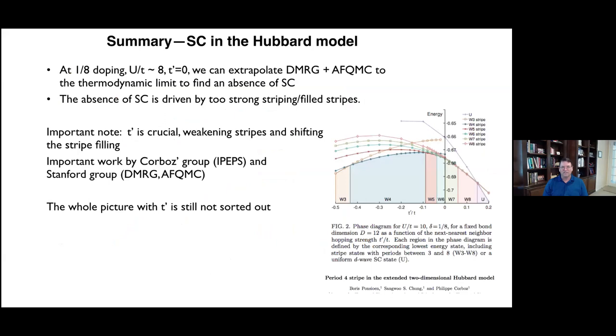Although the energy difference between filled and not filled is very, very small. And you get similar sorts of results even if you're a little bit away from half filling at this particular doping. Okay, so to summarize what we have here, for superconductivity in the Hubbard model, at 1/8 doping, these parameters, we can extrapolate to the thermodynamic limit to find an absence of superconductivity. And this absence of superconductivity is driven by strong commensurate striping along with filled stripes.